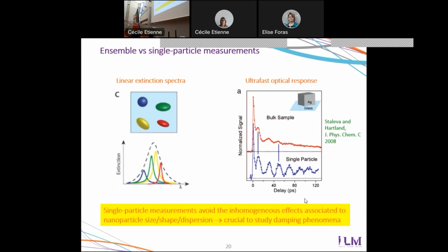The reason is that in the ensemble measurements on a large number of nanoparticles at the same time, the particles vibrate at different frequencies, and so they dephase progressively as a function of time, and this is responsible for additional damping compared to the single particle case. So the key message here is that we can obtain more quantitative information about physical phenomena if one is able to measure single particles, individual particles.